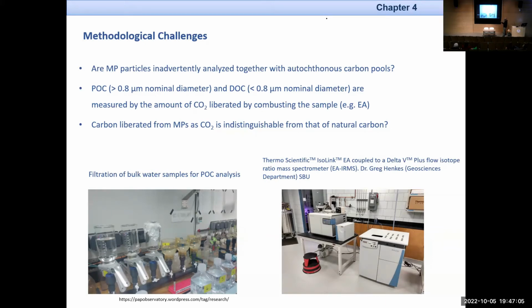And the problem is that we believe that when we capture plastic together with the POC, the organic matter, and we put that sample together in this equipment, the elemental analyzer, everything burns, and the reported CO2 is incorporated in the plastic and the natural signal. So we cannot distinguish what was plastic from what's supposed to be there. So that's one of the challenges that we are facing.